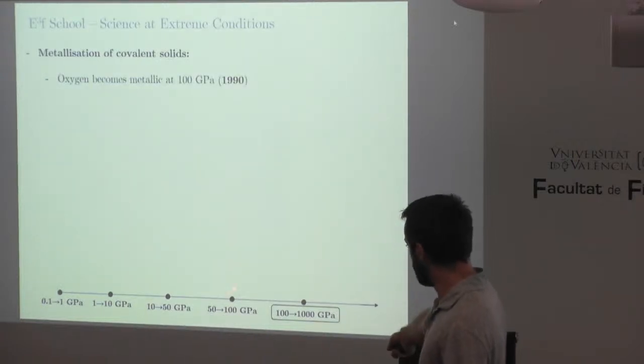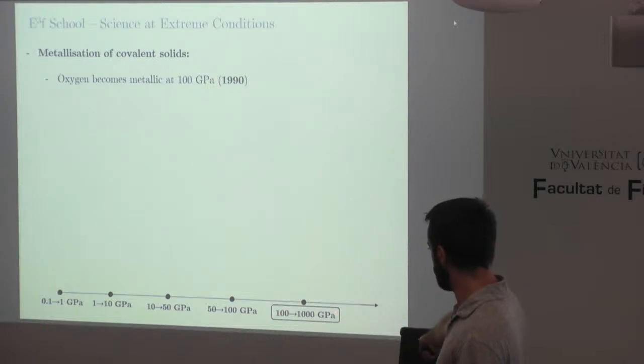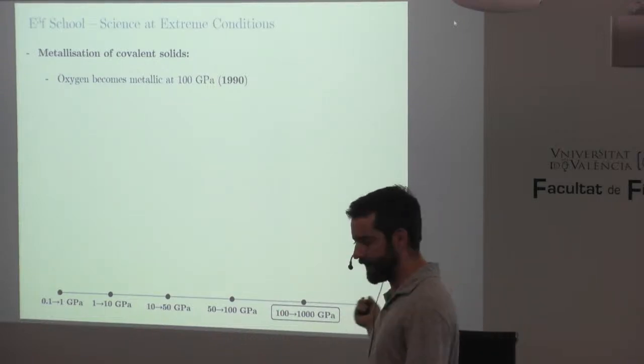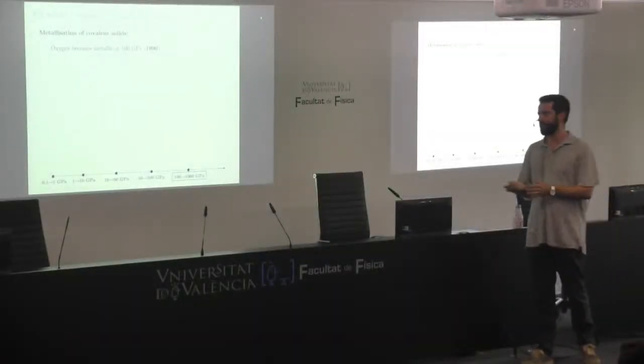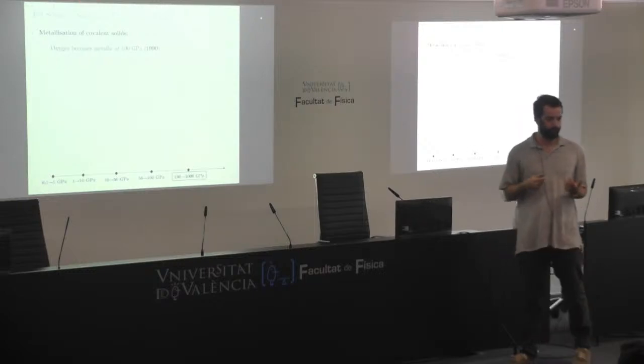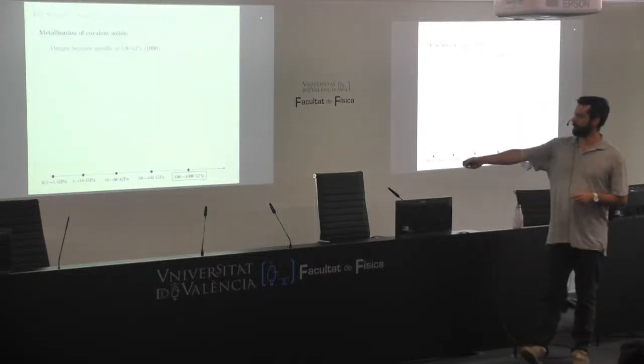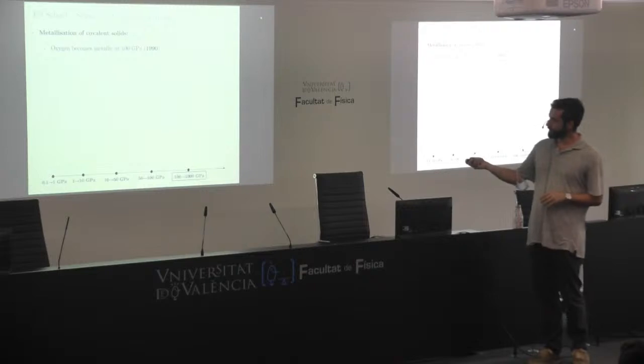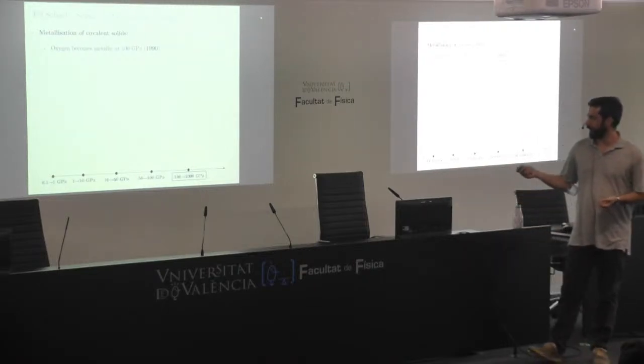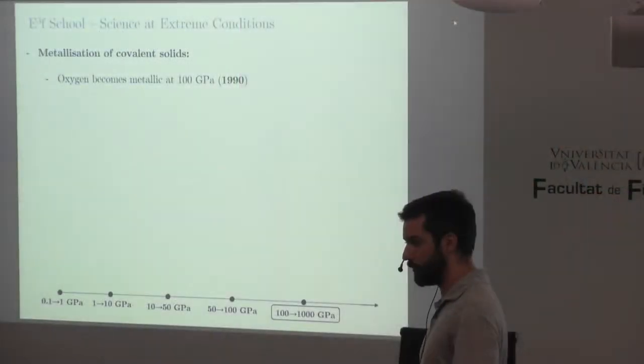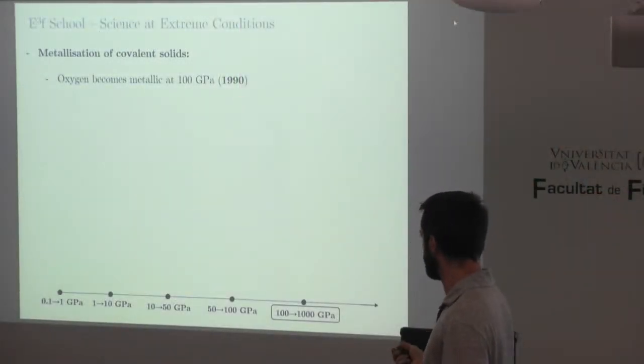Okay, so now we've made our final jump to the highest pressures, 100 to 1000 GPa. At these very high pressures, obviously we have much higher energy densities, and essentially all materials start to become metal, they start to metallize. So previously we've seen carbon transforming into diamond, we've seen the polymerization of nitrogen. In this example, oxygen, which we're breathing this very moment, becomes a metal at a pressure of 100 GPa and low temperatures, I believe. This was first reported in 1990.